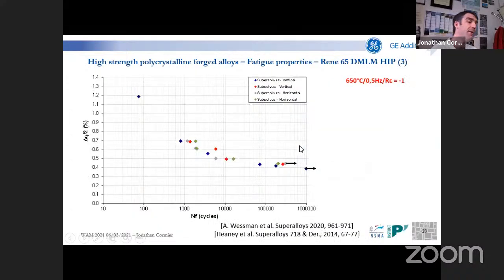And then when we did fatigue test, so this is an SN diagram, half strain range as a function of the number of cycles to failure. Those tests have been performed here at P prime with a frequency of 0.5 Hertz, sinusoidal waveform, fully reversed conditions. And here you can see all the data points we have for the 4 batches of specimens. Something which is really impressive is that we see almost no anisotropy and one single trend, which is almost the same as the cast and wrought material, meaning that this kind of process can be introduced.